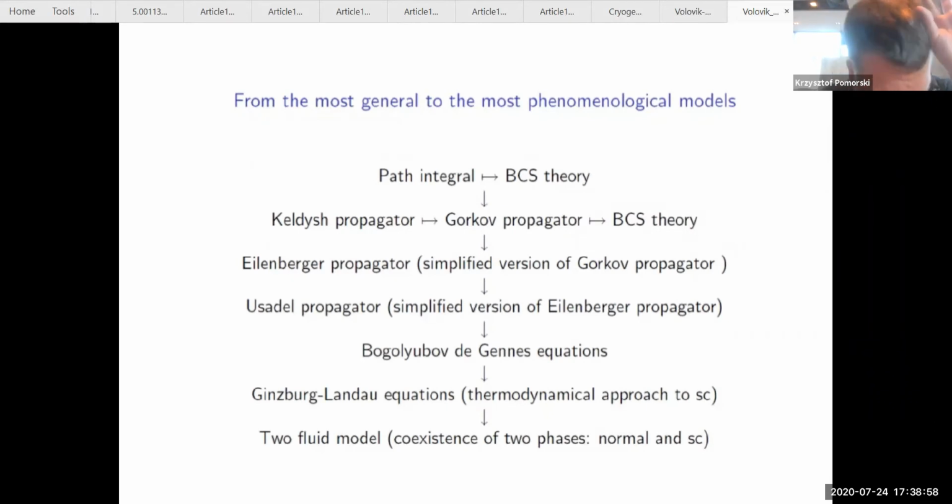When we talk about superconductors, we are talking about quantum correlations on the length of the superconducting coherence length or longer, which is around 3000 angstroms, so about 300 nanometers. And usually wave functions describing electrons are limited to very few nanometers. So that's a different scale.